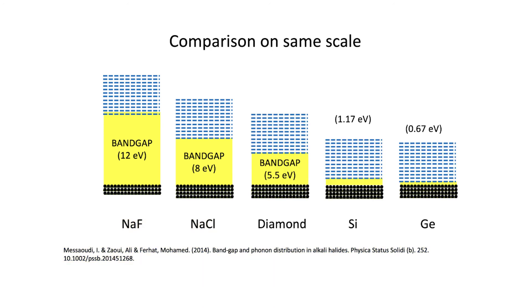Comparing several materials: all five materials are insulators that don't really conduct electricity, though their conductivity isn't exactly zero — you'll always have a few thermally excited electrons in the conduction band. Germanium has a higher electrical conductivity than silicon, and silicon has higher conductivity than diamond. Thermal energy is not the only way to promote electrons — light absorption is another method. The first three materials here are transparent, but silicon and germanium are not, because visible light has sufficient energy to promote their valence electrons into the conduction band. In diamond and the two salts, visible light has insufficient energy for that promotion, so they remain transparent.